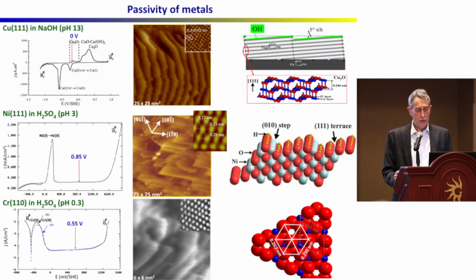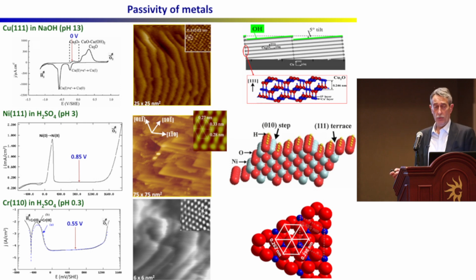So we did experiments along this line, and we looked also at copper, but now we are no longer talking about the underpotential range; we go into the formation of the oxide. This is a cyclic voltammogram for copper. We looked at the potential over this range of potential, and this is a typical image that we get, and that's the high resolution image. So we have really atomic resolution. This is a non-filtered image, and it's recorded in the aqueous solution.